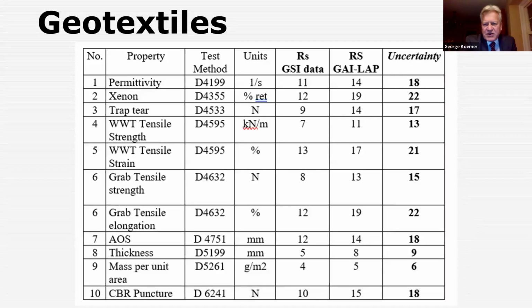So the first table I show you is for geotextiles, and these tests that I called out, the 10 test methods, are typically referenced inside of AASHTO M288: permittivity, xenon arc weathering, trap tear, wide width tensile, grab tensile, AOS, thickness, mass per unit area, and CBR. Here you see the values for RS, which were obtained at GSI, then the reproducibility, which was obtained through the GAI-LAP, and then certainly the uncertainty.